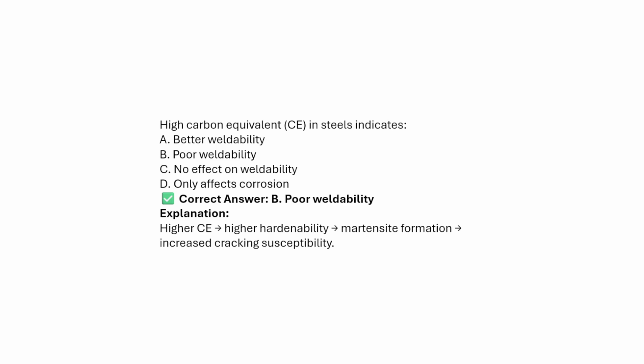High carbon equivalent in the steel indicates what? If high carbon equivalent is present in the steel, it means the material is more hardenable. More hardenable means more martensite formation. That increases the crack susceptibility, so this is not a good thing. Option A, better weldability. Option B, poor weldability. Option C, no effect on weldability. Option D, only affects corrosion. So the answer will be poor weldability, because high carbon equivalent means higher hardness and martensitic transformation, increasing the crack susceptibility.